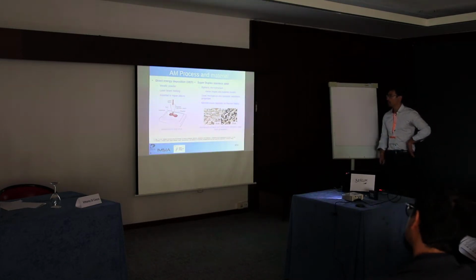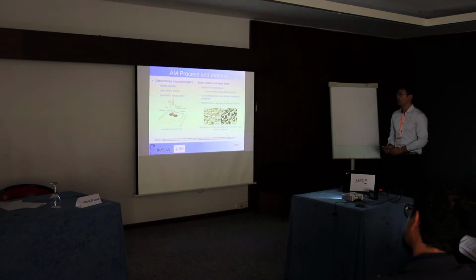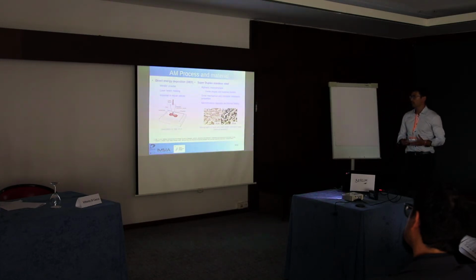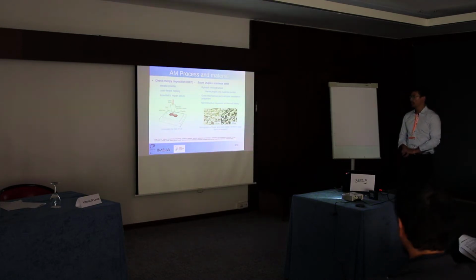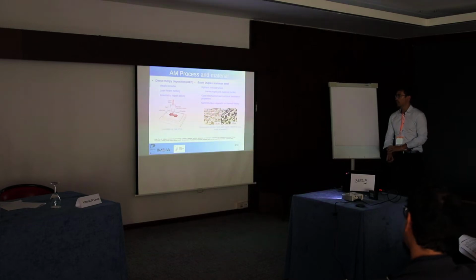Now for the material, it is quite particular in the sense that it has a biphasic microstructure. First, there is the ferrite that is supposed to be more fragile, and the second phase is the austenite, which is in comparison more ductile. This mix gives the material good mechanical properties, as well as good resistance in some corrosive environments.